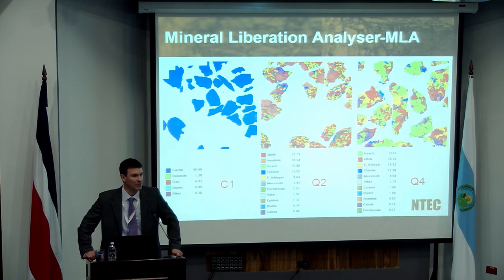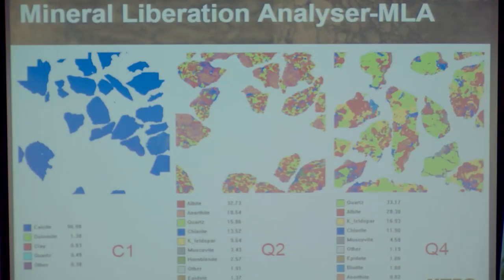And finally, we're very interested in being able to link mineralogy back to adhesion. So although we could do the test and we could end up with different ranges of results, without understanding exactly what the mineral composition of our aggregate were, we're not going to get a nice relationship or at least some kind of information that we can use as a screening tool. So all the aggregates that were tested, all the substrate plates that were made, all went through some form of mineral liberation analyzer, or MLA, which is basically a scanning electron microscope with a special attachment. We can define or at least separate our individual mineral composition. And I've given you three examples there. The one on the left-hand side is a normal limestone. As you would expect, mainly calcium carbonate in nature. That's the dominant mineral or material. Probably 99% of the actual material made up of that particular component.